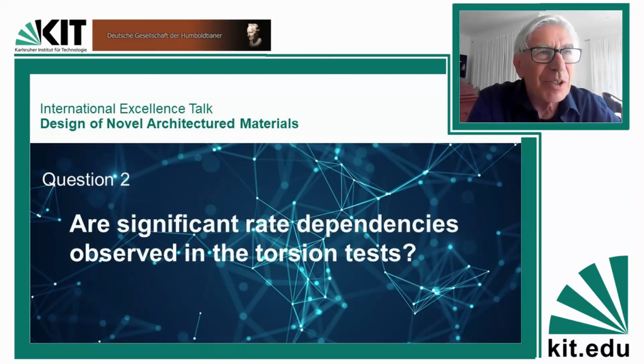It's a very good question, because the answer demonstrates that it's different to the turbulence in fluids, where there is a strong rate dependence. Here it is not, at least not a significant rate dependence. It's really a matter of the strain that you impart on the structure. And the occurrence of this turbulence depends critically on the difference in the stiffness of the soft and hard layer. So it's not a Kelvin-Helmholtz turbulence, which we know from liquids.